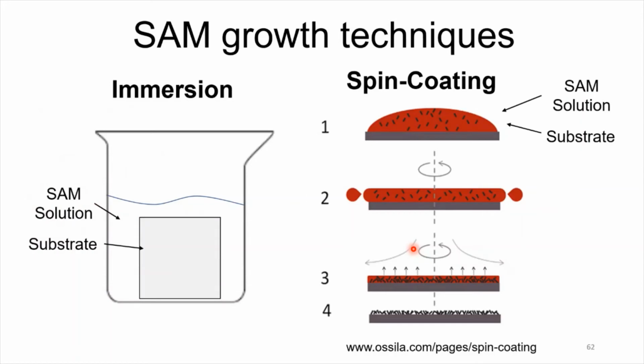And we developed 3 different techniques, or we had taken advantage of 3 different techniques. Our first approach was, of course, well, what if you get just your glass, put it in your monolayer solution, see if it grows. But it wasn't working as well as we expected, so we started looking at other types of processes, and we ended up with spin coating, where you spin at really high rotation speeds, and what this allows is for the monolayer to assemble really evenly on the surface, and the spinning will cause the solvent to evaporate faster than just sitting on top of it.